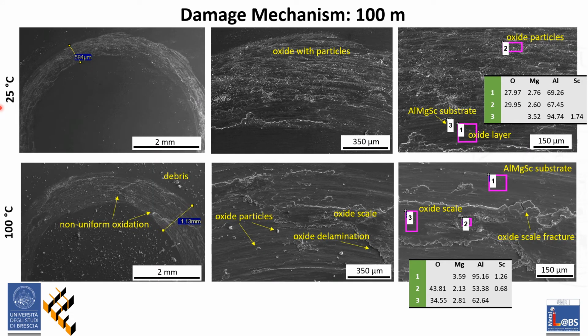Now, let's see what happens at the Scalmalloy disc through SEM investigations. The next two slides report analysis after the first 100 meters. Temperature is indicated on the left, and images are shown at increasing magnification moving on the right. The formation of the oxide occurs at every temperature. In particular, at room temperature, it appears more granular, with also the presence of oxide particles, which reveals greater oxide instability. Instead, at higher temperature, the oxide manifests itself as more compact scales or layers, as can be seen from the images below and in the following slide.